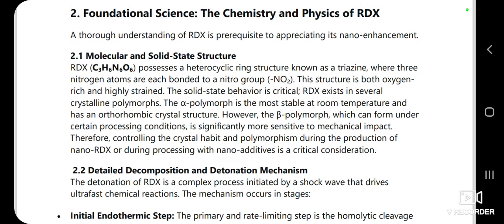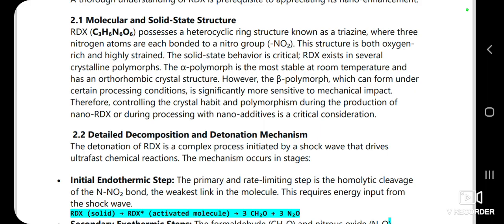Now we see the foundational science, the chemistry of RDX. What is RDX chemically? To appreciate the enhancement, we need to understand what we are enhancing. Here's the RDX molecule, a heterocyclic ring structure known as triazine, where the three nitrogen atoms are each bonded to a nitro group. This structure is both oxygen-rich and highly strained. It is perfect for rapid decomposition, but here's a crucial practical point: RDX crystals come in different forms called polymorphs. One form, the beta form, is significantly more sensitive. So controlling crystal structure during nanoprocessing is not just academic, it's critical for safety.